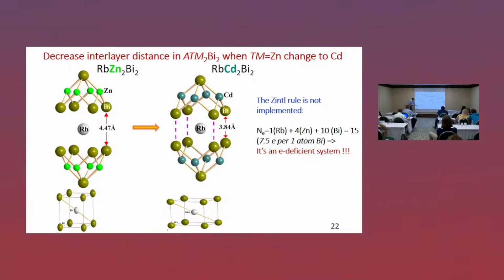because in the polyhedron with rubidium, the distances in the main diagonal are the same in this case and this case. The main diagonal is stable, but the distances between the bismuth atoms in this case are smaller, because this is part of the tetrahedra with zinc. In this case, the distances between the squares in the bottom, part of the tetrahedra with cadmium, are bigger, and we can see that this polyhedron is compressed at the highest point.